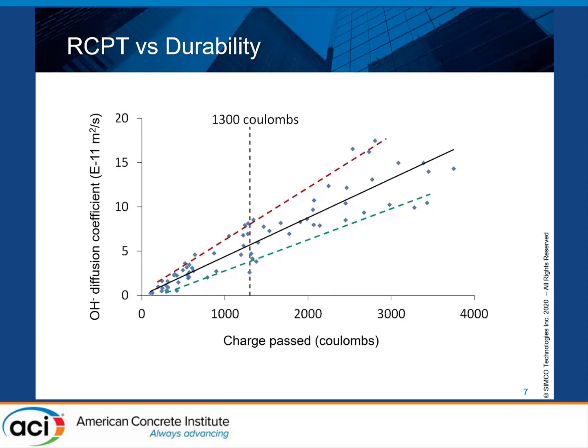Here on that graph, it's a relationship between the RCPT and the durability. So you see it's, and the diffusion coefficient, I should say. So it's much better if we have RCPT. It's not perfect, but you see that there's some kind of correlation between the RCPT and the diffusion coefficient. So if codes incorporate RCPT requirement, it's better than just the compressive strength.